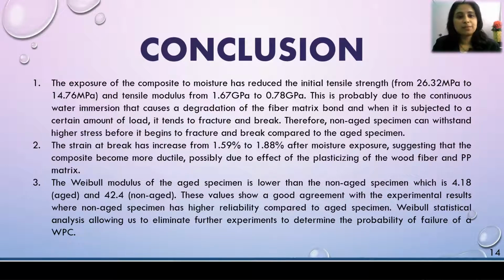Moreover, the strain at break has increased from 1.59% to 1.88% after moisture exposure, suggesting that the composite becomes more ductile, possibly due to the effect of the plasticizing of the wood fiber and PP matrix.